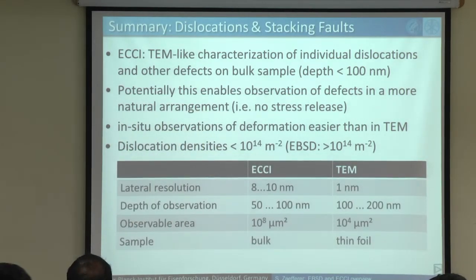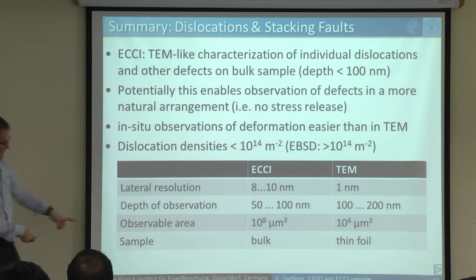And here's a table with comparison. Of course, in lateral resolution, we are not as good as a TEM. For classical TEM, diffraction-based TEM, we have maybe 1 nanometer resolution for dislocations. Here we have about 10. The depth of observation, so how deep in the sample do we look? This is on a TEM foil. It's usually in the order of 100, maybe 200 nanometer. Here we see approximately the same depth. Of course, the observable area is orders of magnitude bigger because we have just a bulk sample. And good, that's bulk sample versus thin foils.